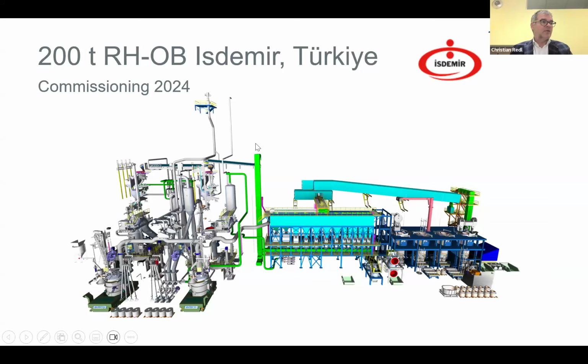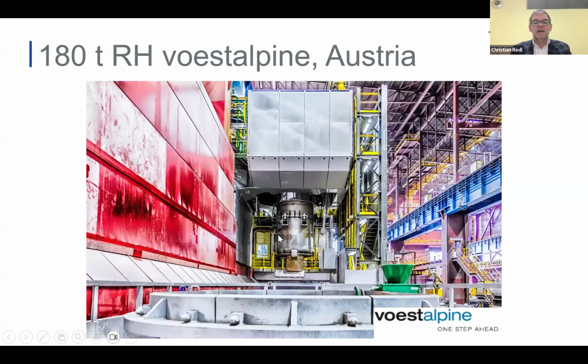As I said, RH degassers are more used for the integrated mills. Here is one example of a plant which was installed and will be commissioned during 2024. It's a 200-ton RH with oxygen blowing for Isdemir in Turkey. You see very huge dimensions for this 200-ton with 2 treatment stations, a very extended alloy adding system for material handling. And this is one example for a 180-ton RH plant at Voestalpine in Austria, where we have installed 2 plants over the last decade.